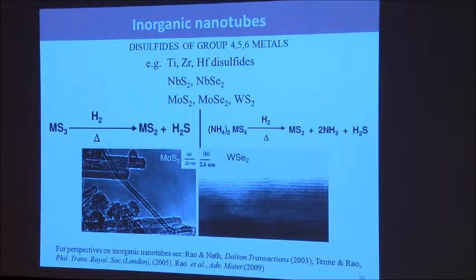These carbon nanotubes, when they were made, immediately we could make nanotubes of various kinds, particularly of the layered disulfides, selenides—I'm just showing you sulfides and selenides. This is the molybdenum sulfide nanotube. Similarly, many other nanotubes, like Boron Nitride nanotube, are very easily made. So this all is a background.